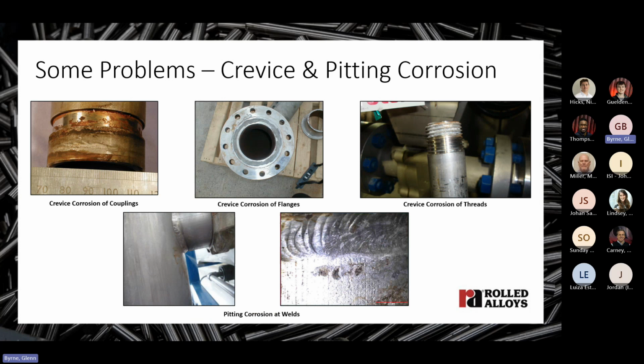So 6% molybdenum alloys and super duplex stainless steels have performed well in our applications around the world, but they're not immune to corrosion in seawater. Crevice corrosion at couplings and at threaded connections and at flange faces, and pitting corrosion of welds can be an issue. It can be relatively trivial, but it can be more serious. The relative cost of super duplex stainless steel is about twice that of 316L. 6% moly alloys, the price is about 2.8 times 316L.